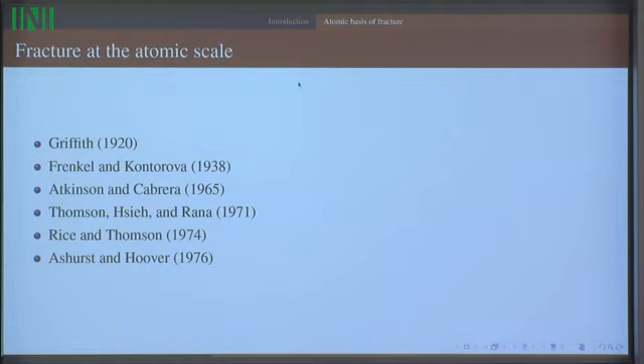Frenkel and Kontorova in 1938, the first discrete model of a dislocation, which is a related singularity. The first dynamical model of a dislocation, again, Atkinson and Cabrera, 65. The first atomic static model of a crack, Thompson, Hsieh, and Rana, 1971. The first estimates for the origins of fracture energy at the atomic scale, Rice and Thompson, 74. And the first numerical simulations of fracture at the atomic scale, purely computational, Ashurst and Hoover, 1976, done at Los Alamos, which had then, to some extent, is now the largest computers.